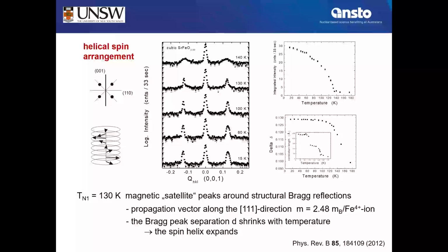So how does it look like? What do we get? That's perhaps also new to everyone who never had a look at magnetic scattering before. You get 2 magnetic Bragg peaks at non-integer positions, 0.13 in that case. Not linked to the crystal lattice at all, it's not integer.